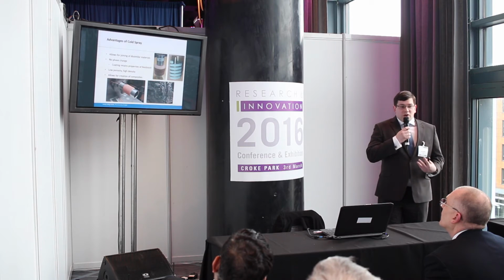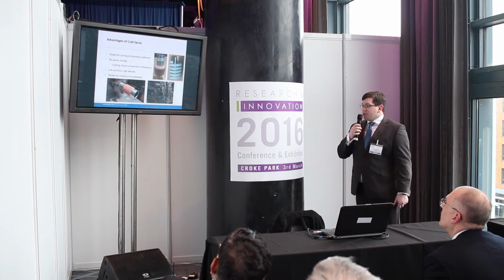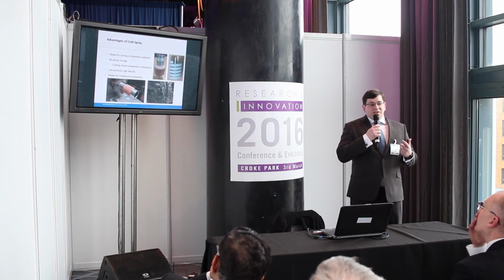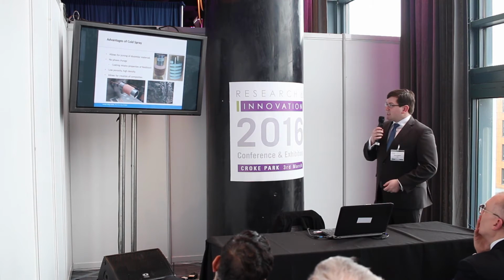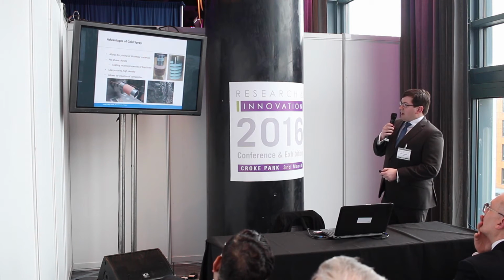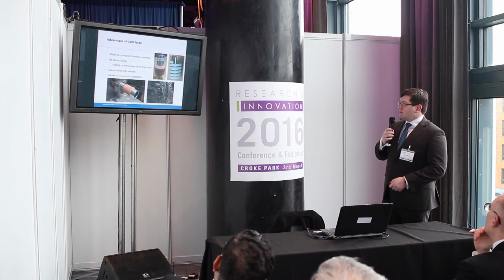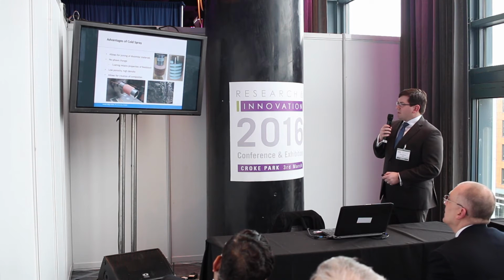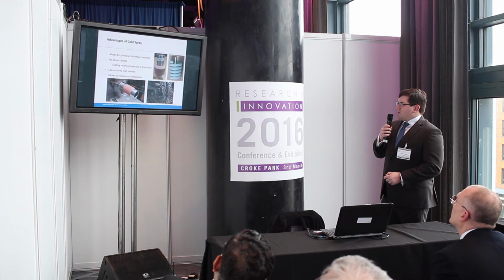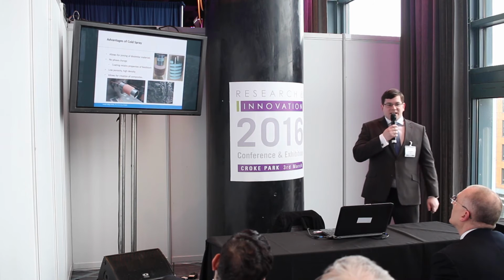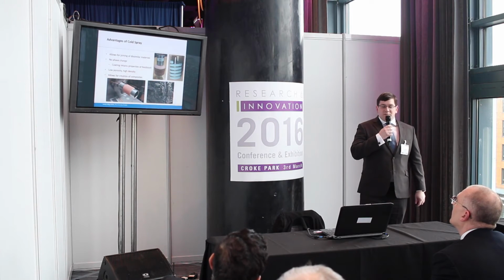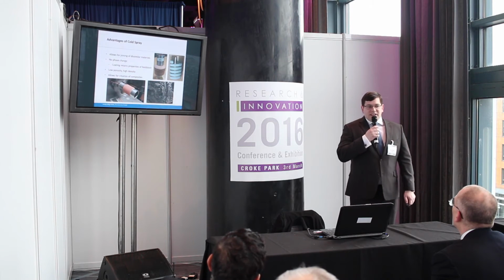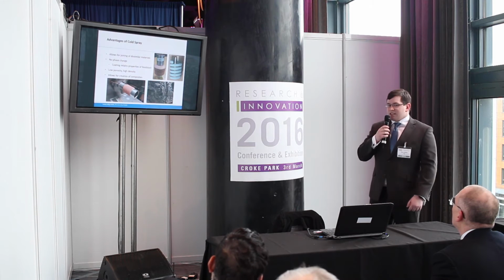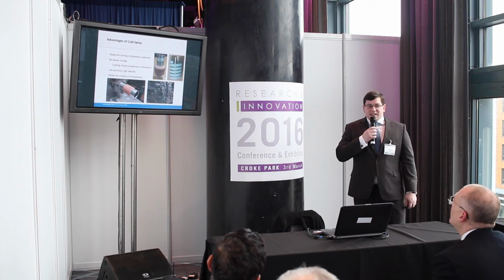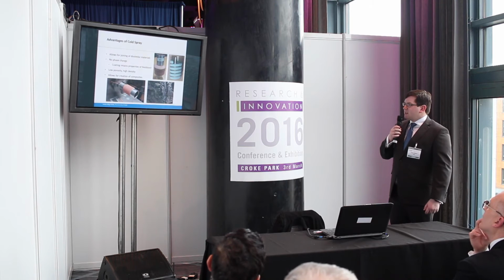So some of the advantages of cold spray, some of the reasons why you might use this over other approaches, other technologies. You can join dissimilar materials. An example of this is shown here, where we have some copper coated onto an aluminium tube, quite a thick deposit. And also shown here, this is one of the ones that we're most proud of, aluminium deposited onto PEEK. So that's aluminium deposited onto a sheet of polymer. The aluminium is electrically conductive, and that is a very thick layer. Again, that's about 1.5 to 2 millimeters thick, deposited onto a polymer.